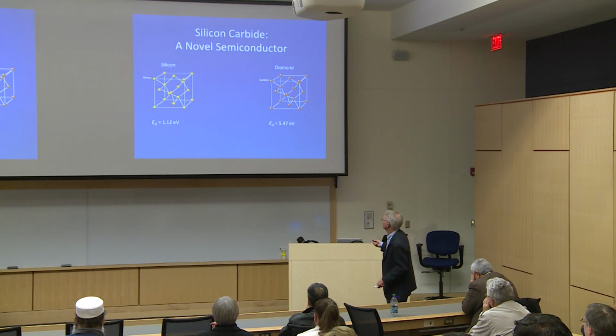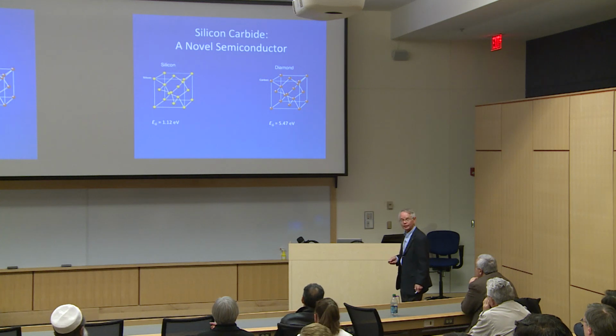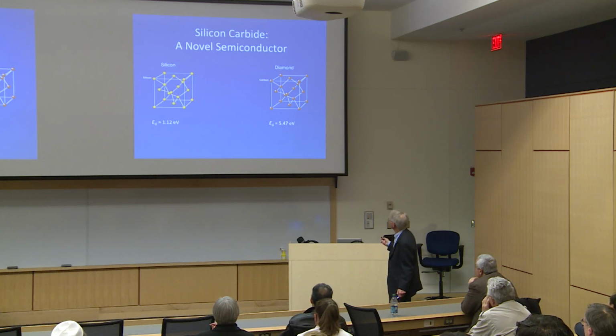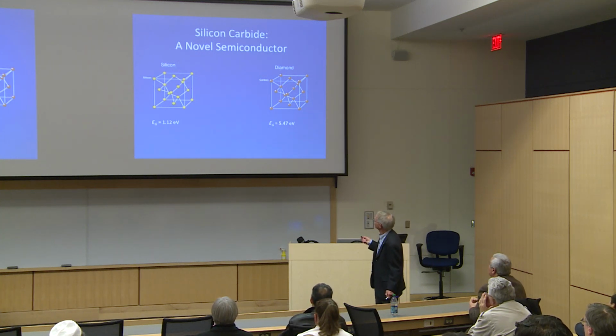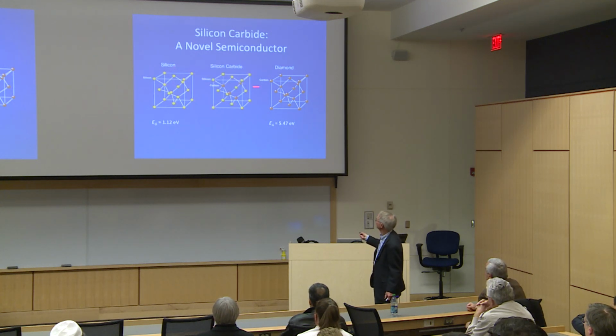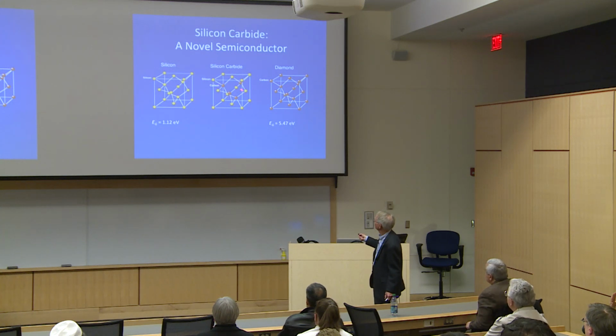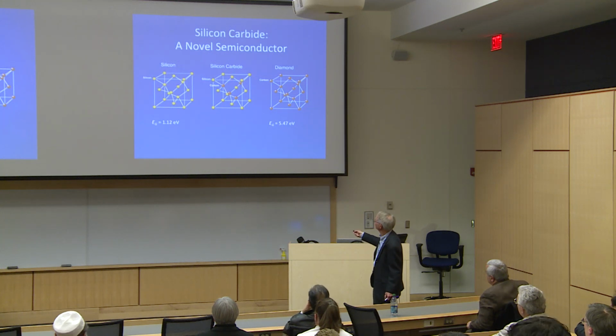In diamond, it's a much higher band gap. It's about 5.5 electron volts. Silicon carbide is a material that is half silicon and half carbon. It looks like either silicon or diamond, but half the atoms are carbon and half are silicon. Each carbon bonds to 4 silicon nearest neighbors. Each silicon bonds to 4 carbons. You can't see the others because they're in the cell above.